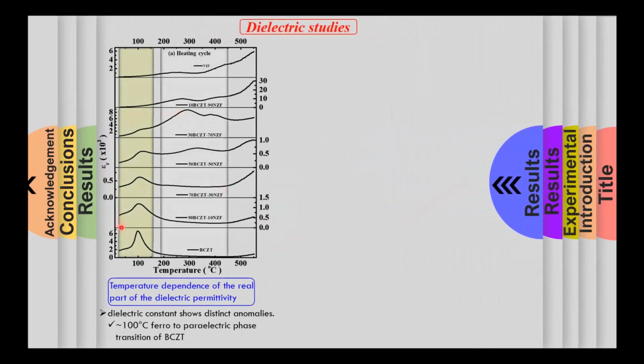In the dielectric permittivity curve with temperature, this is the curve for the pure piezoelectric BCZT sample. It exhibits a relatively sharp and well-defined dielectric peak at around 100 degrees Celsius, and this corresponds to its ferroelectric Curie temperature. And we see that as we keep on adding different weight fractions of nickel zinc ferrite, this peak gradually weakens, and absolutely no peak of the piezoelectric phase is observed at very high concentration of the nickel zinc ferrite. At 50 weight percentage and beyond, we start to see the dielectric response from the magnetic transition of the magnetic phase.